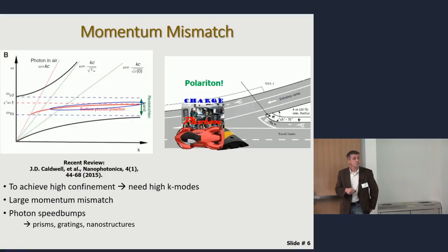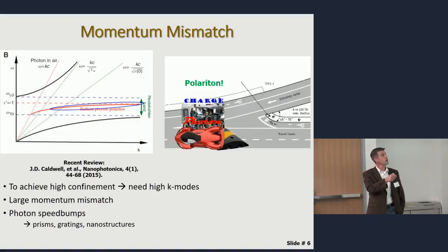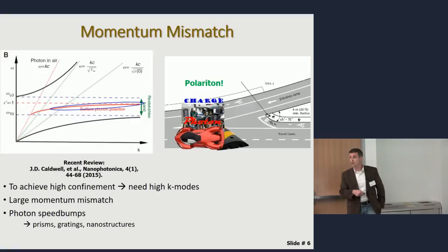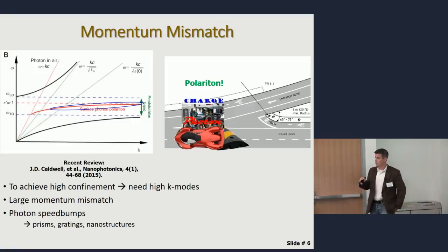So where can this speed bump come from, right? Well, I can induce a higher index prism, right? Or induce a grating whereby I can take this light line and tilt it, right? And in so doing, I'm basically hitting different areas along this curve. This is how Kretschmann geometries, where you're coupling through various angles through a prism, can allow you to map out this dispersion.